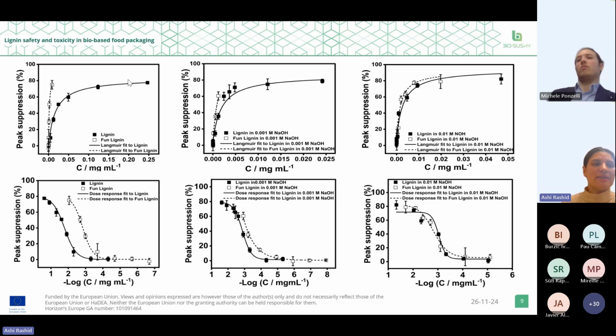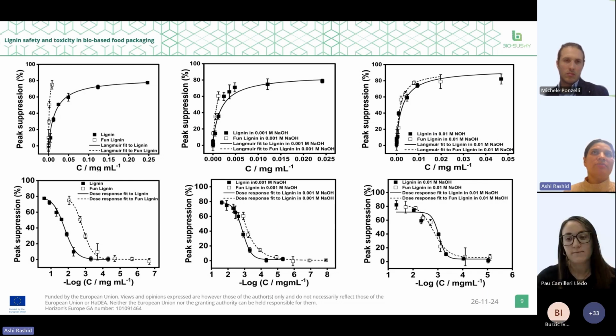Here we can see that the peak suppressions are relatively higher in case of functionalized lignin compared to unfunctionalized lignin in the absence of sodium hydroxide. Keeping in view that all other conditions are the same, and we are not using any sodium hydroxide in this case, the only difference is the presence of the silane functionality on the surface of the lignin, which presumably has contributed to the overall enhanced interaction of the functionalized lignin compared to the unfunctionalized lignin.